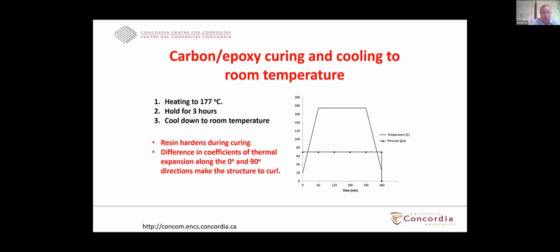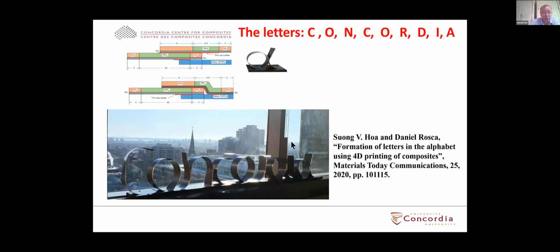Also in this case, after you lay down the stack of material, you have to cure it. You have to heat it up to 177 degrees centigrade, hold it for 3 hours, and cool it down. So this is basically a standard conventional way of making composite material, and we use commercially available materials. Over the last few years, we managed to make a few structures using this technique. And the structure we made is the word Concordia.